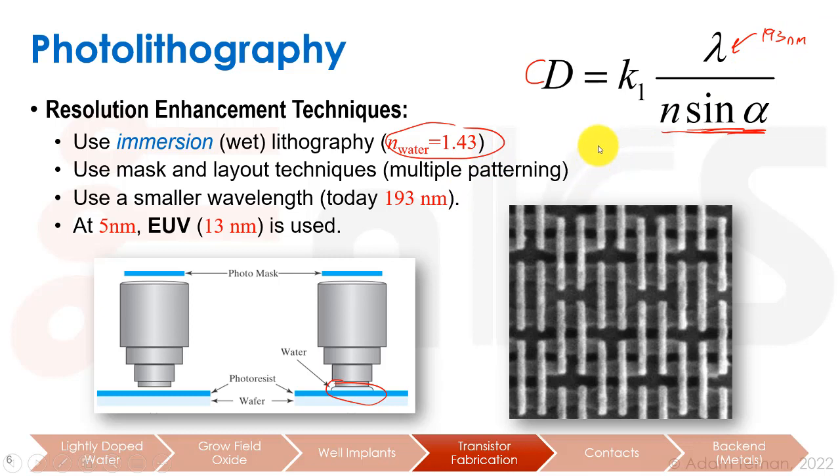That being said, it costs a lot. We need a lot of masks to do it. A lot of masks means a lot of expense, a lot of time, a lot of variation, problems with alignment and so forth. And so finally, at TSMC 7 plus, or at the different 5 nanometer processes, we were able to change over to the EUV 13 nanometer laser, and that's what is currently being used for the most advanced processes. That really enables us to reduce the number of masks by a very large amount, and also to get less variation and fewer alignment problems and so forth.